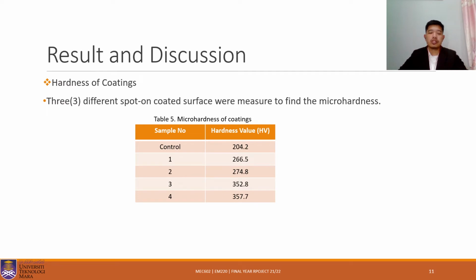Next, we move to result and discussion. Hardness of coating. 3 different spots on the coated surface were measured to find the micro hardness and tabulated in table number 5. Control sample has micro hardness value 204.2, sample number 1 266.5, sample number 2 274.8, sample number 3 352.8, sample number 4 357.7.